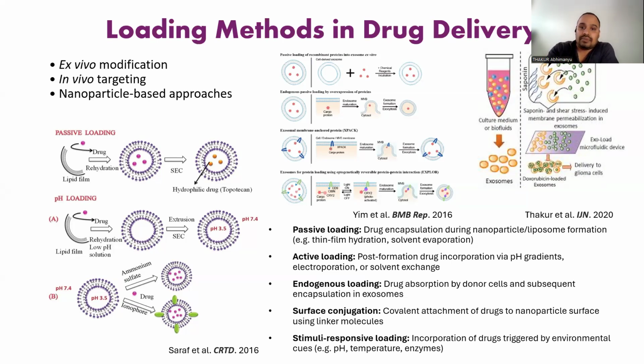Again, in case of nanoparticles, various scientists have even shown that approaches like encapsulation and delivery, and the passive loading methods such as thin film hydration or even solvent evaporation, facilitate drug incorporation during the nanoparticle or liposome formation. And in case of active loading techniques, for example, post formation strategies like pH gradient or even electroporation or even solvent exchange enhance the drug loading efficiency.